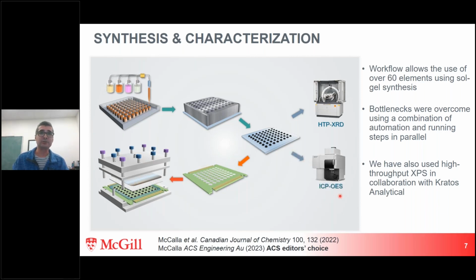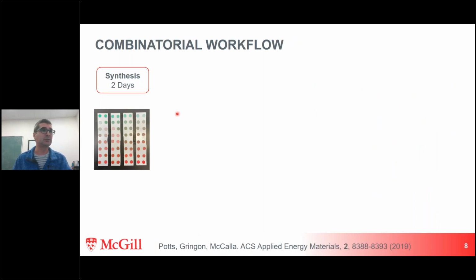Okay. We also do a lot of elemental analysis. So after we heat at 850 degrees, we lose some sodium. So we have to figure out how much sodium is left and whether we made what we think we made. So we do elemental analysis, but the main high throughput that we do is structure and the electrochemistry. And I'll actually show a little bit of XPS today, which was also very helpful in understanding what's going on in these materials. Okay, and we do lots of automation. Here we could use a robot, or sometimes my students find it's just faster to pipette and they do it very well. So we use whatever we need to increase our throughput so that we can do some really interesting science. And so the workflow looks something like this.